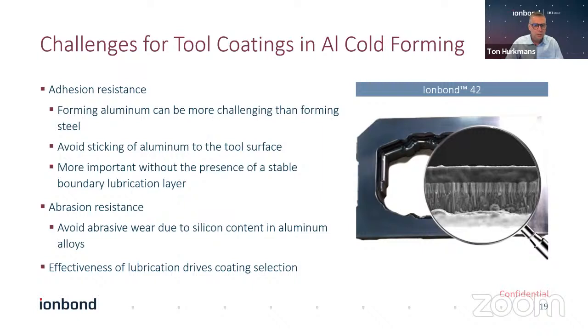But in this typical application, forming of aluminum can be a challenge, more so than forming steel. And that's mainly because the aluminum tends to stick to the tool, and that needs a lot of nasty cleaning steps to keep the tool in production, but also gives a lot of scrap pieces and cracks in the aluminum if you try to form it with a classic designed tool without coatings.